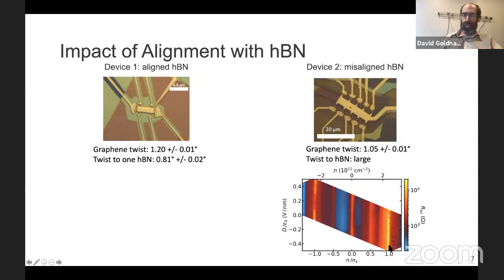with the vertical axis. That's telling you that the electric field normal to the plane doesn't matter very much in this case, but the density does. And so, for example, this feature at 0.5 means when in a situation that you would normally expect to be just a partially filled band, a metal, instead there's a pretty high resistance. So this is something that's familiar from magic angle graphene, that you can get correlated insulators that occur at partially filled bands. So now let's look at the one with aligned boron nitride.